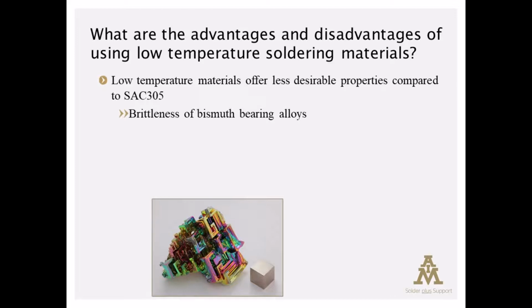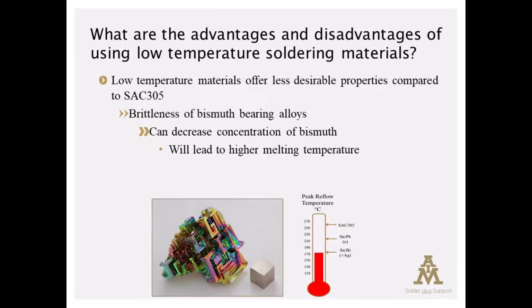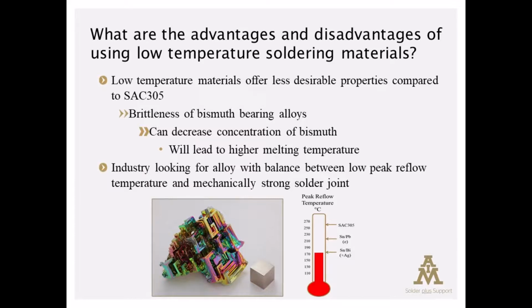We can decrease the bismuth content to try and reduce the brittleness or improve ductility. And then the flip side of that is that I start to raise the melting temperature, and that's where the balancing act takes place. From what I can see, AIM and our competitors are working diligently to come up with an alloy that is the best compromise between these two worlds: a low peak reflow temperature and a sufficiently mechanically strong solder joint.